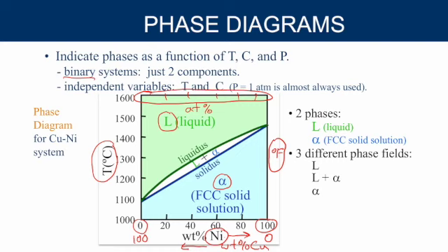And then we have a region where both can exist at the same time. Part of our material is liquid, the other part is solid. So the number of phases is 2. There's just L and there's alpha, right? The phase regions, or phase fields, we usually call them regions, there's 3. There's the liquid region, there's the liquid and solid region, and there's the completely solid region. So 3 different phase regions, 2 different phases exist on this graph.